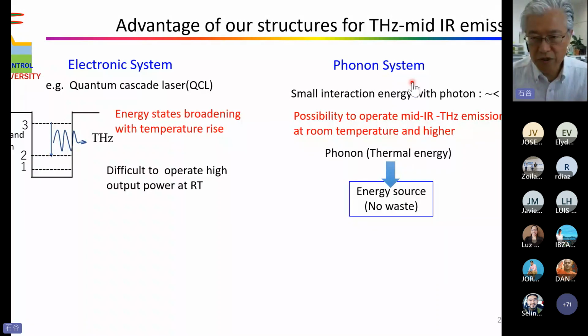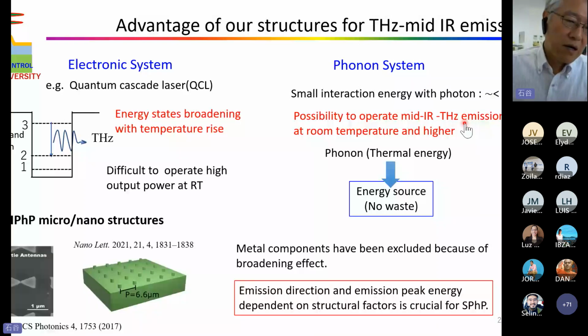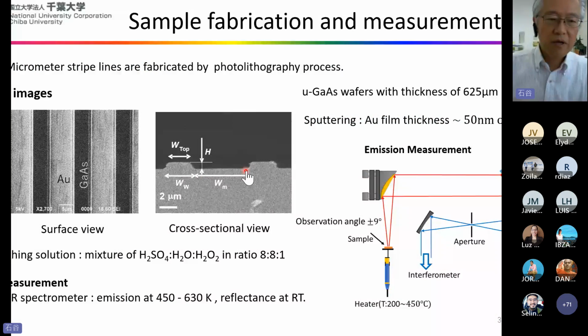But when we utilize a phonon system, no cooling is necessary because heat energy is the energy source of the light. So there is no problem with heating. Conventionally, surface phonon polaritons using nanostructures have been developed, but in this case there is a big problem: the wavelength depends on the emission direction. This is a very severe problem. But in our case, it is not such a nanostructure, so it is very easy to fabricate.